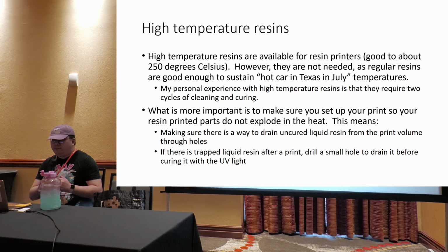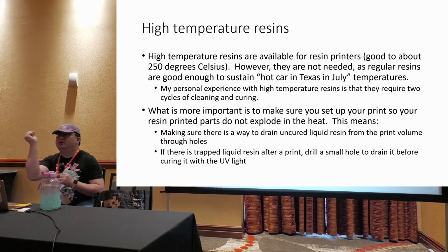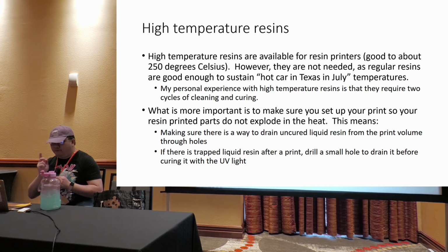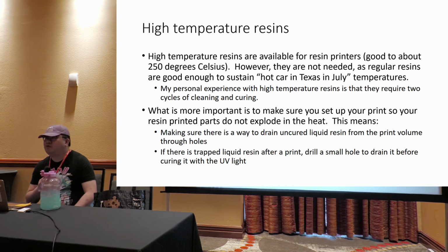First thing, you cannot do this in the design phase, you have to do it during the slicer phase. So make sure that during the slicer phase, you have holes drilled into the part. And if after printing you realize there's still trapped resin, before you cure it, you have to drill a hole yourself using a drill and drain out that unused resin. Otherwise, I guarantee you, your resin will explode, and you will not like it. All right. Any questions?